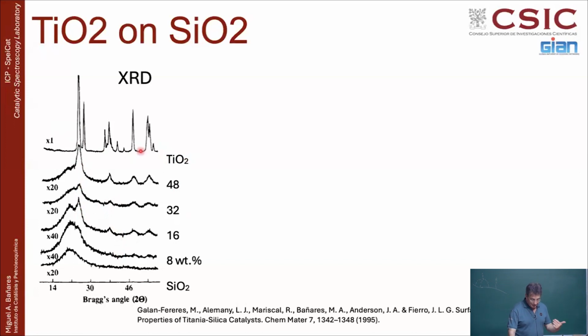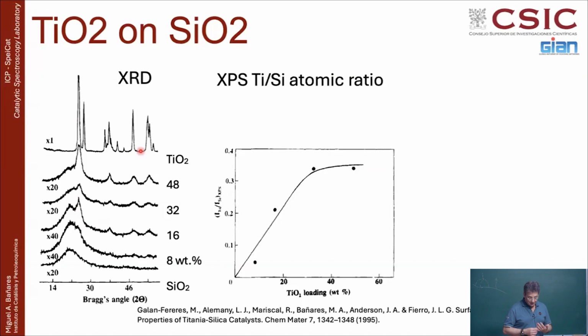Now, you are adding this. If you use another complementary technique like X-ray photoelectron spectroscopy, XPS, you can look at how many titanium atoms you have at the surface. And basically what the XPS will see is close to the surface. So you are having more and more titanium on the surface, so the XPS will see more and more titanium. But there is a moment when, to the XPS, there is no more titanium, because this titanium starts to grow on top of itself. So you only see the titanium on top, but not the titanium behind.